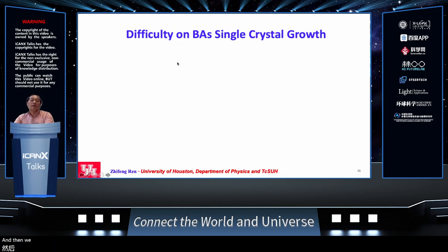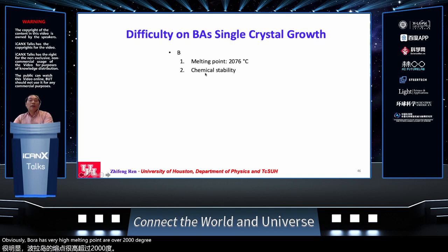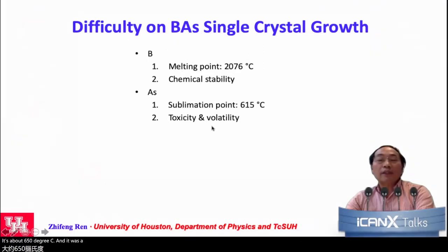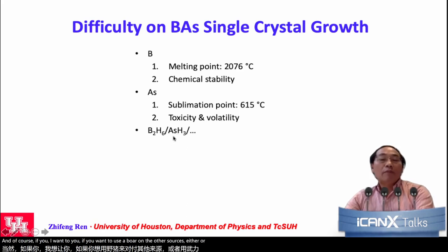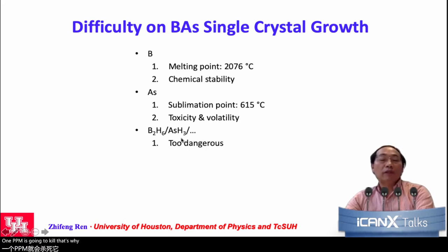So that means this material must be very difficult to make, and we looked at the details of why. Obviously, boron has a very high melting point, over 2000 degrees C, and is chemically very stable. On the other hand, arsenic does not have a melting point but a sublimation point at about 650 degrees C, and is also very toxic and very volatile. If you want to use other sources, either diborane or arsine, they are very toxic. 1 ppm is going to kill you. That's why you've got to be very careful and use these two sources instead of a solid source.